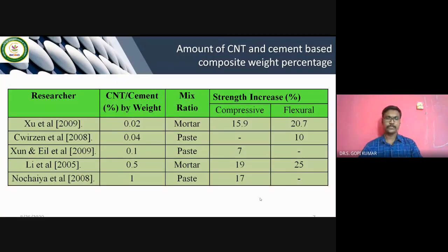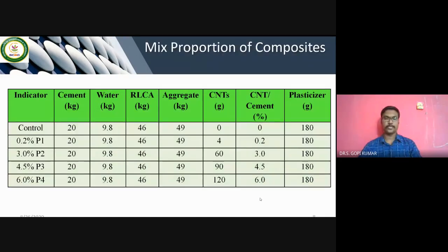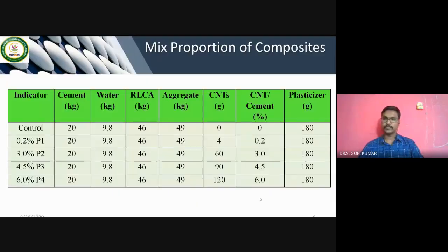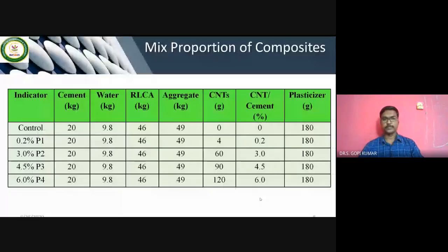And with this literature, our work has been focused, where the carbon nanotube and cement percentage were categorized as control, 0.2, 3.0 percentage, 4.5 percentage, 6.0 percentage, and the amount of carbon nanotube used were the respective grams, where for 6 percentage 120 grams were used, and 90 gram for 4.5, 60 gram for 3.0 percentage, and 4 gram for 0.2 percentage. And for the rest of the components, cement, water, recycled lightweight clay aggregates were displayed.